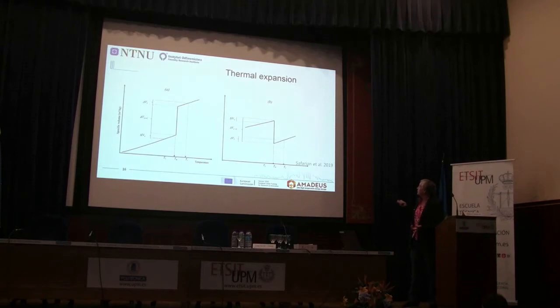However, silicon is one exception from the rule, right? So silicon will go like this. So again, if we have a liquid going down in temperature, it will go down. However, the solid phase will have a higher volume compared to the liquid phase. So it means that the silicon will expand about 10 to 11% during solidification.